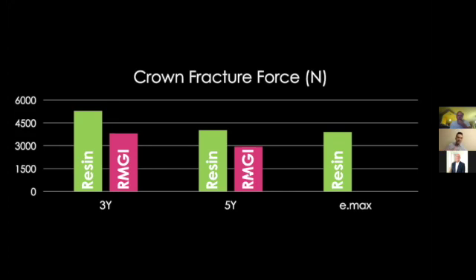But one problem that a novice like me runs into is when I'm doing lithium disilicate crowns, particularly in the posterior, if they're kind of thin and I'm doing a try-in, I've had issues with fracture during try-in, and that's when the 5Y is stronger prior to being bonded. If you're doing a try-in, it's a little bit more foolproof. It's dummy-proof for dummies like me. So it gives me an opportunity to try it in without having to worry as much about fracturing it. And also there are always those friends who are like, Nate, I don't want to bond, I don't want to use resin cement. If you're going to be using RMGI cement, again, I think that's maybe a place where the 5Y is a little safer.